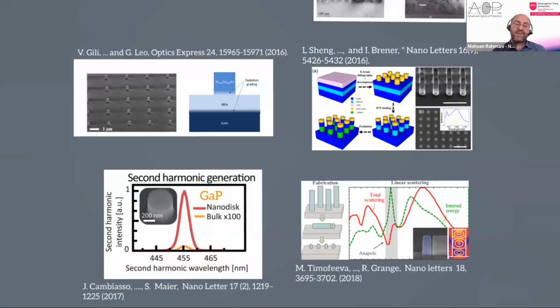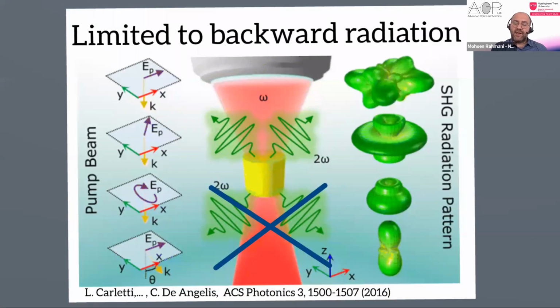And it was followed by several other efforts. The group of Stefan Maier just used a gallium phosphide wafer and etched it down, and they still showed that you can get good results, although it's on the same substrate. And also the group of Grange made these nanowires, and they cut them and generated some gallium arsenide nanoparticles, which enable getting these high nonlinear signals.